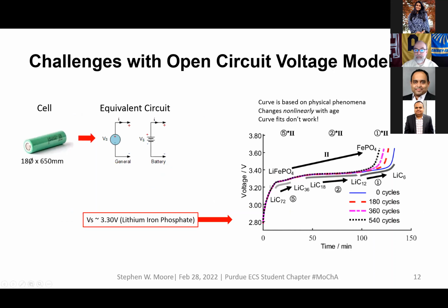And you can see that these little inflection points that we looked at earlier, these inflection points down low on the curve, they all stay the same, but the upper end changes. So if you tried to curve fit this, it would be really difficult because some of the inflection points don't change with age and other inflection points do change with age.